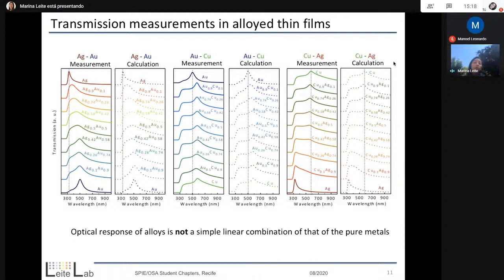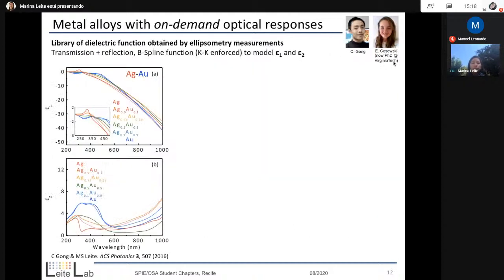So we had to essentially measure that. To measure permittivity, we combine transmission measurements with reflection measurements, and we use ellipsometry for that. And basically, what we did was to essentially measure and model. It's not a measurement only. Once you do an ellipsometry measurement, you have to model as well. In this case, we're using B-spline as our mathematical function. We make sure Kramers-Kronig relations are enforced at all times, otherwise it would be a physically impossible result.